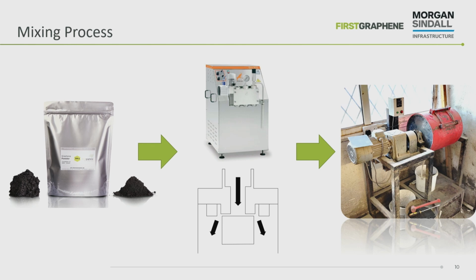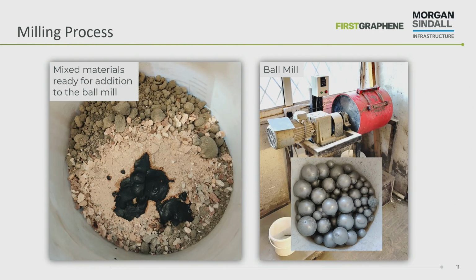We then went on and did lab testing in these small-scale cement mills. So you can see there the grinding aid, that's that black paste there with all the dispersed platelets. Once you start to disperse the graphene, it has a very high surface area. So even low loadings of graphene in a dispersion will cause it to really increase in viscosity as that surface area is exposed. That's it in there with all the additives, the clinker and the gypsum and the limestone. We passed it through the ball mills.